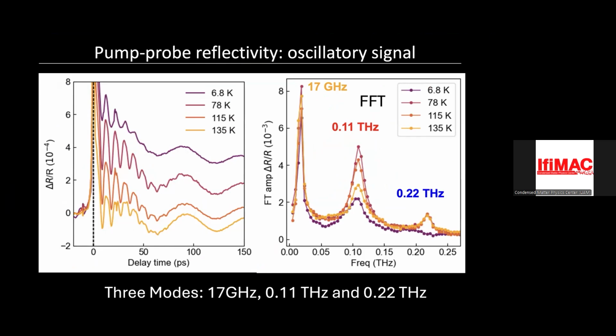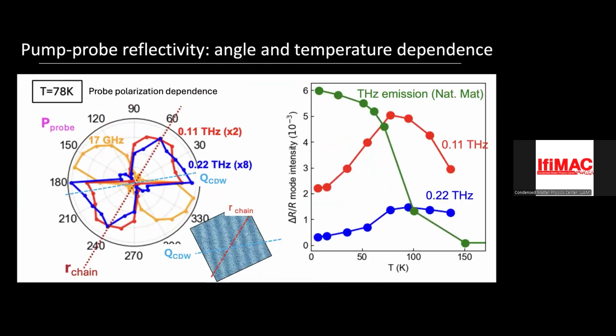Yeah, because of the temperature difference. A lot of this analysis and the idea of the massive phason rests on this strange temperature dependence, this sudden increase in amplitude at a very strange temperature, which has nothing to do with the CDW transition. So this increase in amplitude is really zero here. Also, the X-ray studies were measured at around 150. The phase mode is zero at 150. You see nothing. Even in STM, we see nothing.